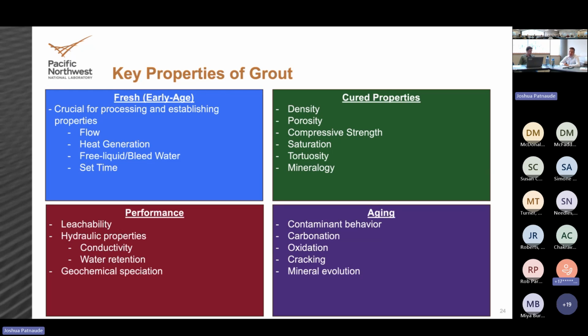The degree of saturation. So once you've made the material, how much free water, how much of those pore spaces are filled up. When we do liquid waste immobilization, that saturation point is near 100%, and it will stay near 100% for the majority of the life of that material, even if it's sitting out in the air in the Hanford subsurface. These materials like to retain that water, and if new water comes by, they want to suck it up to continue those hydration reactions. And then the resulting porous network, how tortuous it is, so how tough that pathway is.